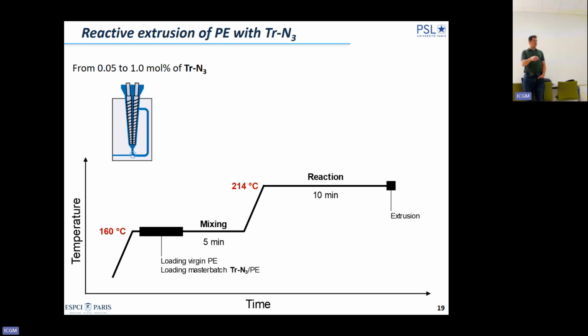So we go at 160 degrees Celsius above the melting point of PE. We introduce the PE. We introduce our triazine azide in a master batch because even though it's a very low loading, it's difficult to introduce a drop of it. So we prepare a batch.